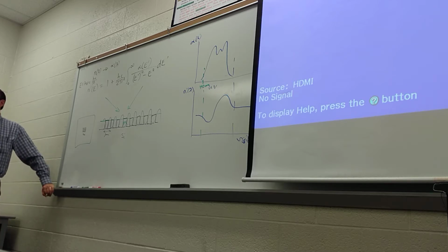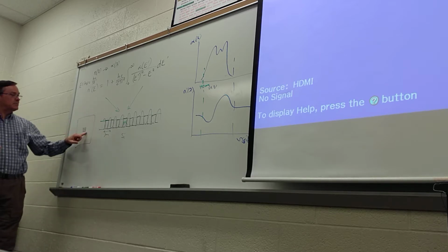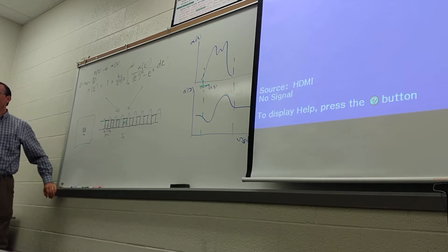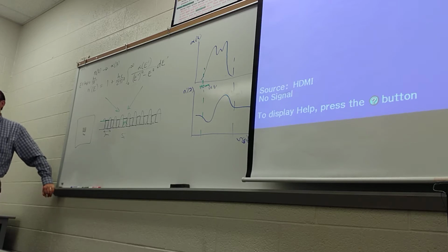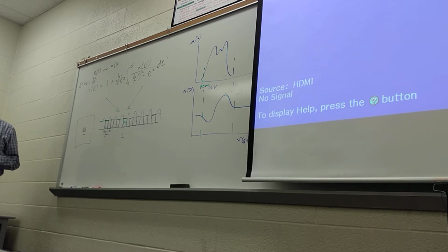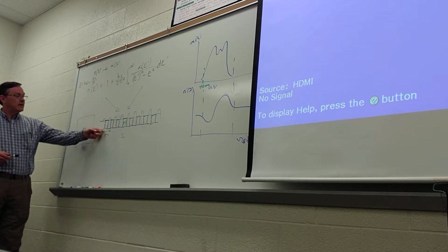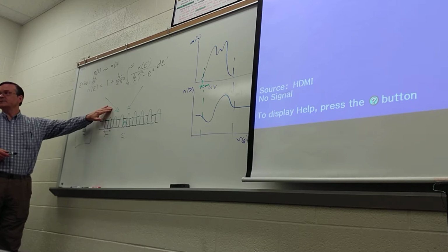That's tough. And the only way it works is if you get really good contact between the mask and the photoresist. The only way to get good, or good enough, contact is using a vacuum contact mode. It's the only way to do it. And if your aligner does not have a vacuum contact mode, forget it, it's not happening. So the poor man's way of getting these kinds of features is just to do interference lithography.